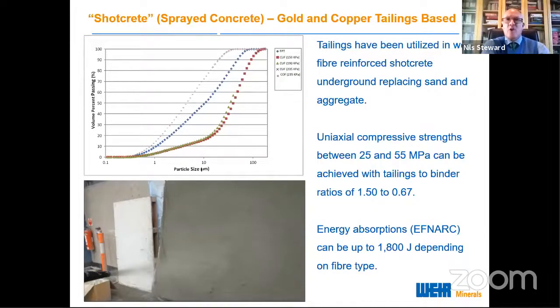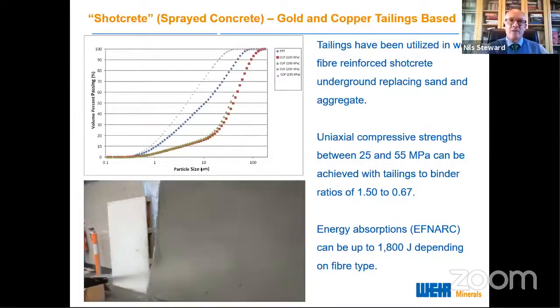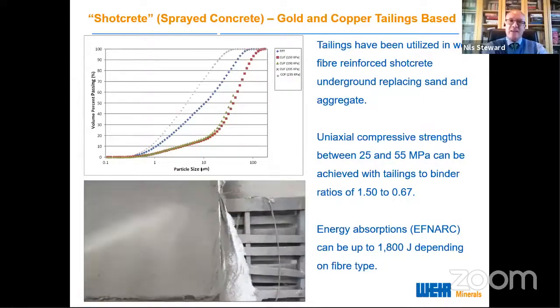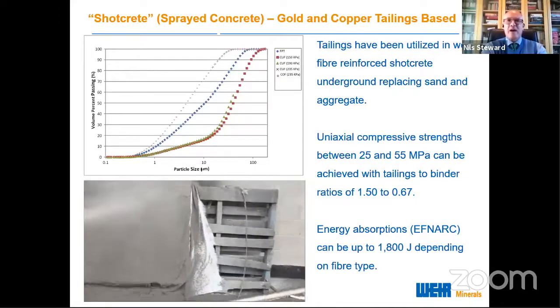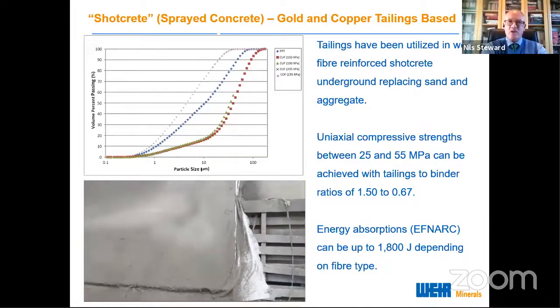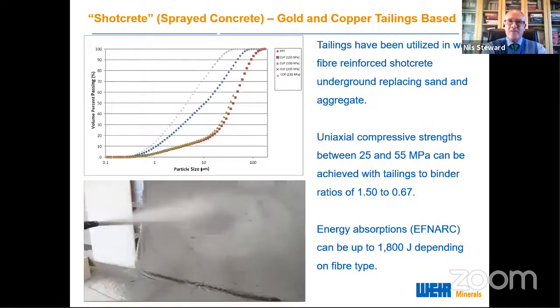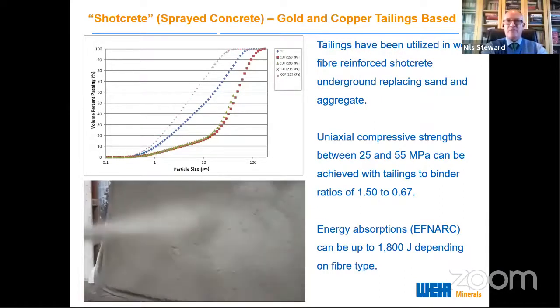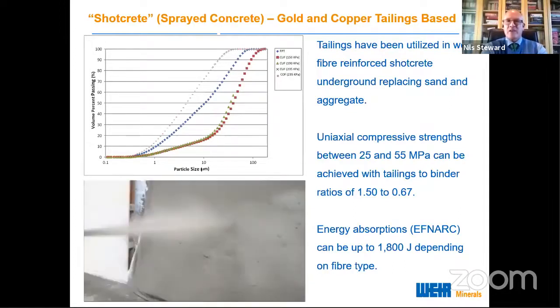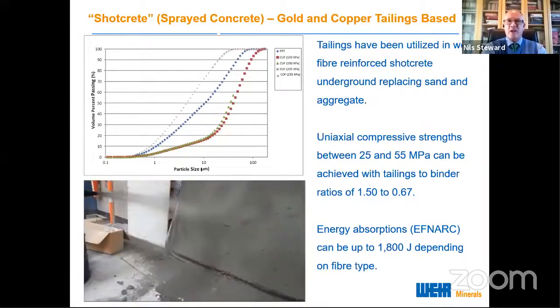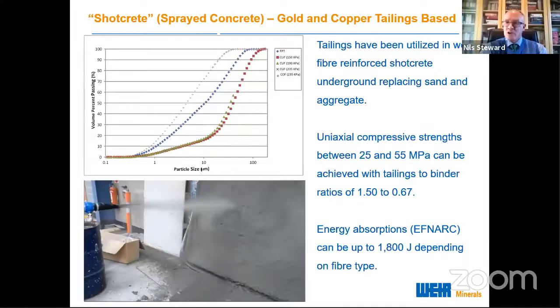The other product, sprayed concrete. We've done this again on various gold mines, both on surface and underground. And it's 100% tailings. There's no aggregate in this. What's very interesting with this wet shotcrete is that it has very, very low rebound, as you can see from this, and compressive strength between 25 and 55 MPa can easily be achieved. Energy absorptions, anything up to 1,800 joules, depending on what type of fiber you use in it. We tended to use polyfiber.